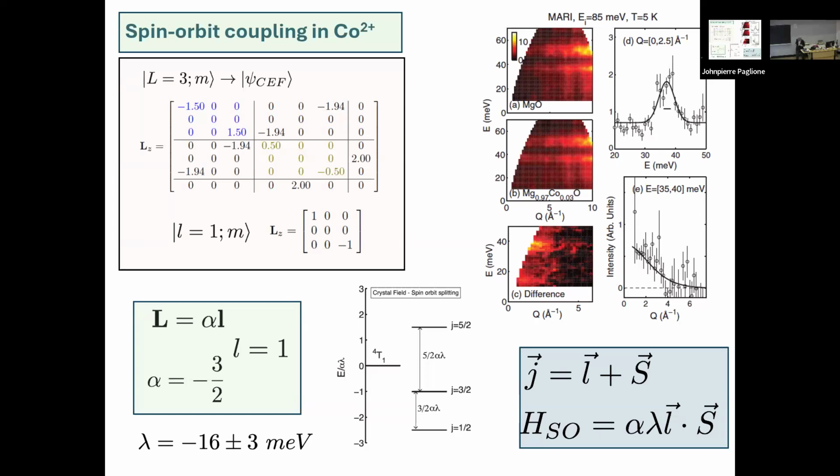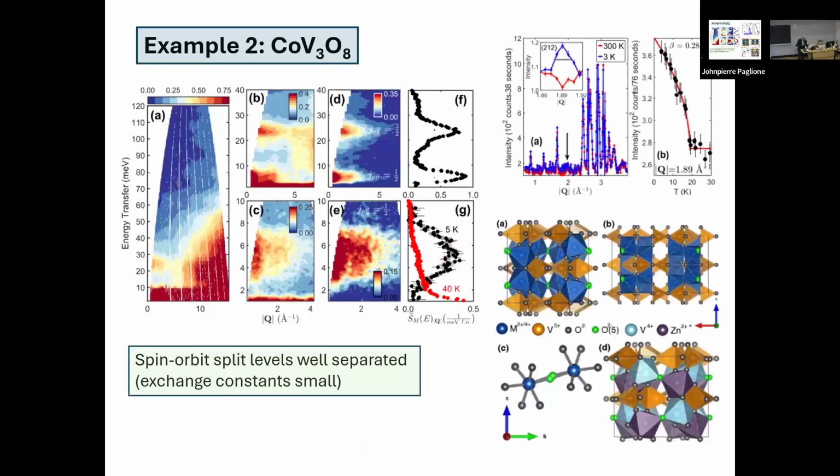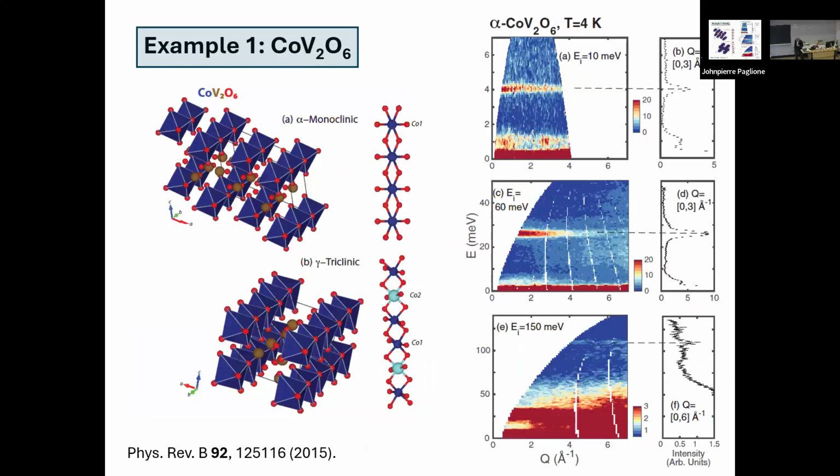Now, in condensed matter physics, I think in magnetism, this bit of physics I've been telling you about doesn't matter, but it does in a few cases. So let me just explain a case here. This is the case of cobalt vanadium oxides, cobalt 2+, and it turns out this first spin-orbit transition going from that effective J = 1/2 level up to 3/2 here is about 25 to 30 millielectronvolts. So it's about kBT at 300 Kelvin.